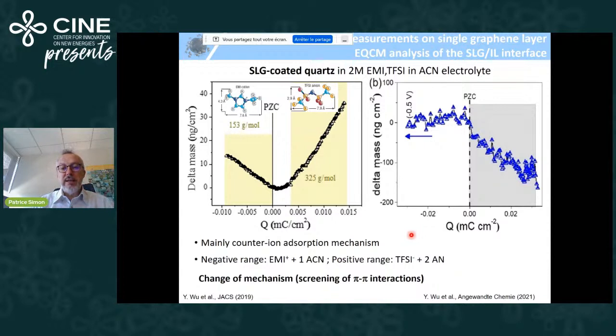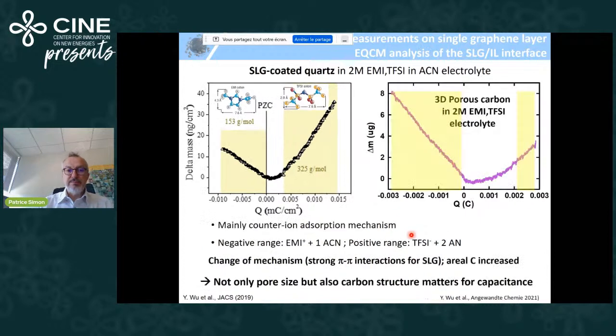And just by adding the solvent, by screening these pi-pi interactions, we completely change the charge storage mechanism. Now, if we compare the SLG in 2 mol per liter EMI TFSI in acetonitrile with 3D porous carbon in the same electrolyte, you can see that we still have a difference in electrochemical behavior, because the charge storage also changes.